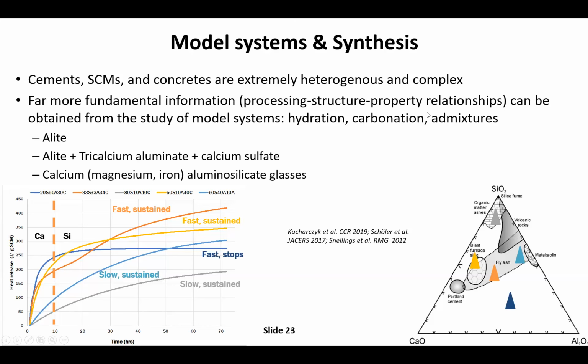And then we said, hey, what's the reactivity going to look like? So ultimately, we want to do a little bit more than this. This is still ongoing. But essentially, you see multiple different behaviors, where now we're talking about reactivity kinetics, which we did not really talk about. In a couple of cases, you get slow and sustained, where the heat is slowly increasing. In some, you just get a rapid increase and then it slows down. And in others, you get a rapid increase which then continues as well. So the initial portion is largely controlled by calcium because it has a huge effect in polymerizing the glass. The later effect is controlled by the silicon, presumably because if you don't have enough silicon, you're not really forming much of a dissolvable glass in the first place. Obviously, you want to relate this with structural parameters, not just calcium and silicon. And that's something that we are working on.